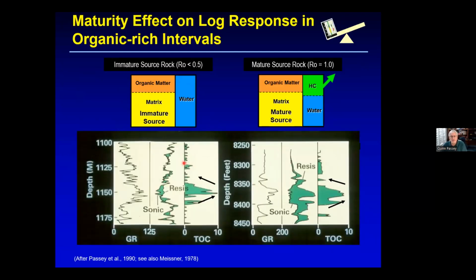Now, here was a case, and this is from the Duvernay in Canada. It's Devonian age, where here we can see this high gamma ray shale, but this is low maturity. It hasn't generated any hydrocarbons, and so the resistivity is really low. The same formation in a deeper part of the basin, you can see the resistivity is really high. It's easy to spot this, but in general, you go back and use a different calibration for when it's immature and when it's mature, but you can still see those two major packages of TOC. In this case, the one on the right is mature; the one on the left is immature, and hasn't generated any hydrocarbons.